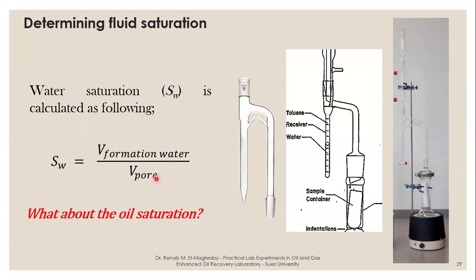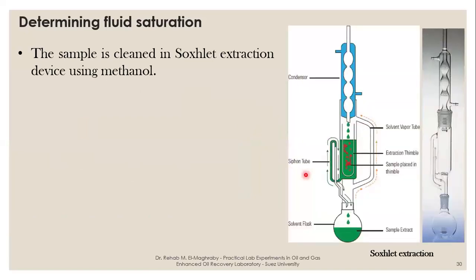Okay, but we know the volume of water. What about the oil? Because it is a non-destructive test, we can just get this core and clean it. Clean it using Soxhlet. So again, in this methanol and toluene mixture, we add the core plug here in the Soxhlet. As we heat this toluene and methanol, it will evaporate to the top and then condense drop by drop, clean the core from any oil, any water available, and go to the reservoir back again.